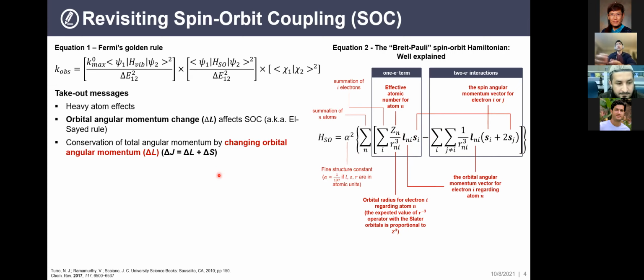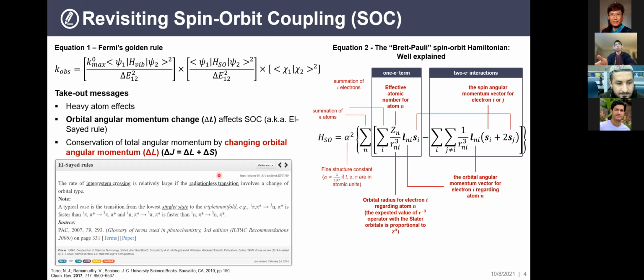And basically, the very fundamental physical law is that we need to conserve the total angular momentum during any process. And during spin-orbit coupling, let's say your triplet state needs to emit the light, which involves an intrinsic spin flip process. So your spin angular momentum has changed. And to conserve the total angular momentum, you have to use another way to compensate that, which is through the so-called orbital angular momentum change, which is very well stated in the well-known El-Sayed rule.